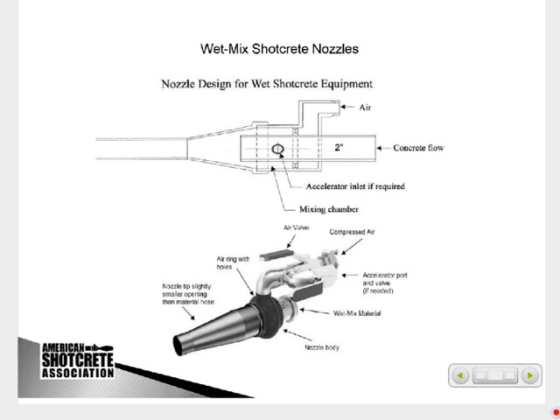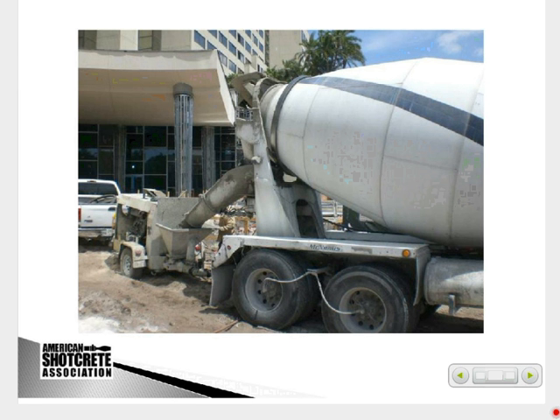We can also add accelerators. A lot of times in tunnel work where you want to shoot it and have it set very quickly, or for instance, that lighthouse project I showed you, where we want to set before the tide came up, you can use accelerator in wet mix. And there's special ports that are put in to inject that material into the flow. Typical wet mix is delivered in a ready mix truck. It's the same concrete that we can order for cast in place. The biggest difference is we tend to go with a smaller coarse aggregate, maybe a 3/8 to ½ inch maximum size for the concrete.